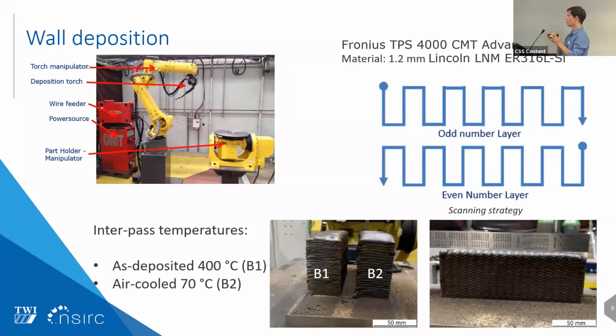And here, for wall B2, we implemented a cooling system between the layers. It was pulsed air on the surface, and we monitored the temperature until it was below 70 degrees Celsius. So we have a final interpass temperature below 70 degrees Celsius. I'll explain a bit more as to why we did that.